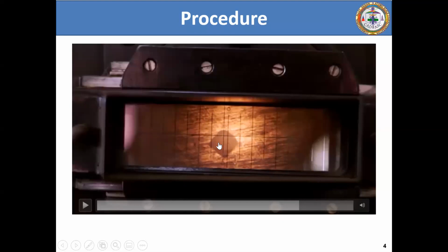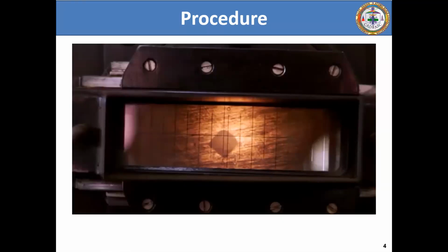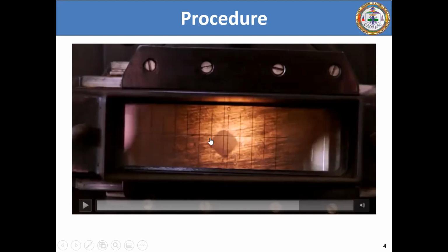Okay, so you can make a note of this: there are two possible cases where this might happen. It is because of repeated usage of the Vickers indenter, or the diamond pyramid indenter. The sides might have got rounded up because of continuous wear and tear, continuous friction. This is called a barreled indentation.